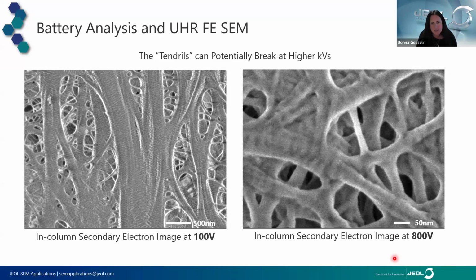And we need to be at these low voltages because separator material tends to be very thermally sensitive. So it's susceptible to beam damage just from imaging. If we use higher voltages, we might break these fine, thin tendrils, or may even make the pores expand as the material degrades. And that would mask what the true structure of the separator material really is.